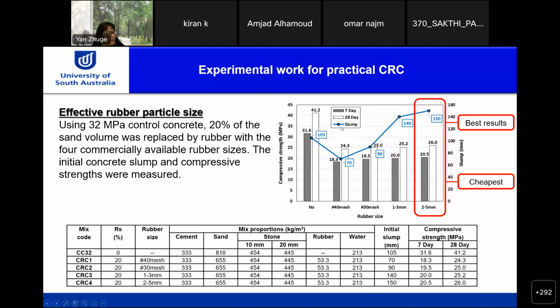And this is the slump test. So the control one was 105, then it reduced to 70 for 40 mesh, increased a little bit for 30 mesh, and increased again for the 1 to 3 mils. And again, for 2 to 5, we get a very flowable structure with good workability. It increased to about 150 mils. So therefore, we found out 2 to 5 size of the rubber with 20% volume replacement was really the best result, and also the cheapest result as well, because 2 to 5 mils rubber was much cheaper than the 40 mesh or 30 mesh.